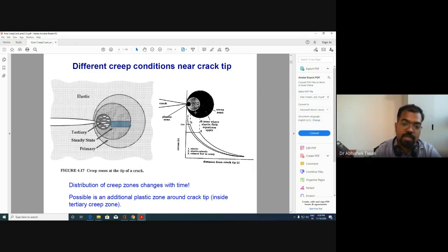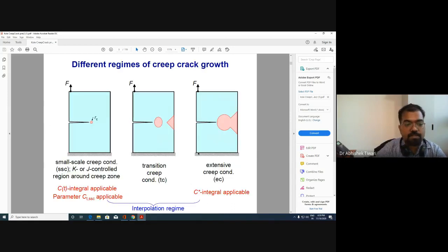So if creep zone is very small in comparison to plastic zone, then you can apply elastic plastic fracture mechanics, because you can ignore creep zone. But if plastic zone is very small, and creep zone is much bigger than plastic zone, then you cannot ignore creep, but you can probably ignore plastic zone, or you can apply plastic zone correction. So you can assume the crack to be virtually grown to the plastic zone radius, and you can then account for the creep deformation. So then three conditions can happen once you have creep deformation.